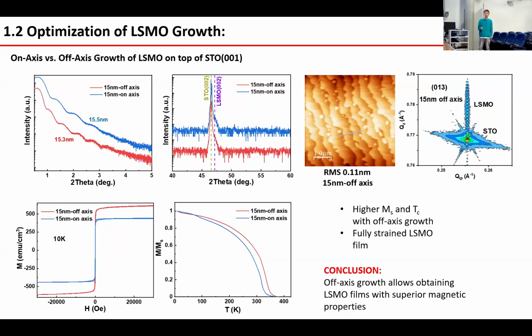Grown on STO(001), we grow an identical thickness of around 15 nanometers of LSMO, calculated by X-ray reflectivity. The theta-2theta curve shows a very clear single LSMO peak without any other impurity phase, and also a low roughness surface obtained by AFM image. The reciprocal space map shows the LSMO and the STO have relatively similar in-plane parameters, indicating coherent straining and growth on top of the STO. However, the DC magnetic property is quite different, where the magnetization and the TC are relatively higher with the off-axis. So we utilize off-axis growth of the LSMO to achieve the higher magnetic properties.